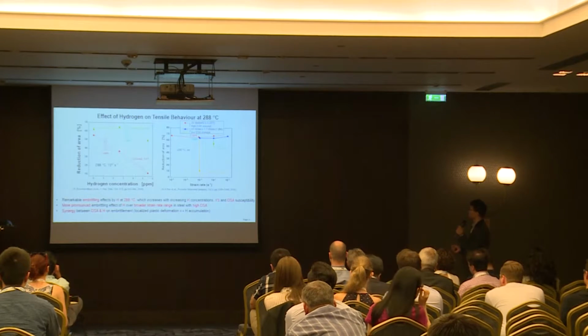And in addition to that, DSA can also play a role. So the red and the orange lines here were the tensile tests with the high DSA material, before and after the hydrogen charging, and the blue and green lines were the tests for the low DSA steel. So it's quite clear that you can see there's a wider strain rate range for the high DSA steel, and the hydrogen embrittling effects were stronger in this case. So when we are investigating the hydrogen effects at such high temperatures, yield strength, hydrogen level, and DSA susceptibility are more important parameters.